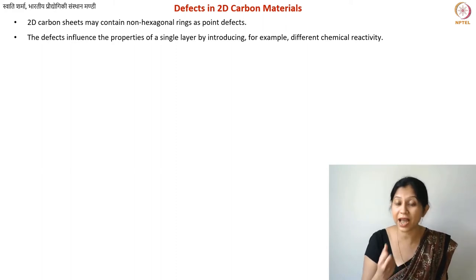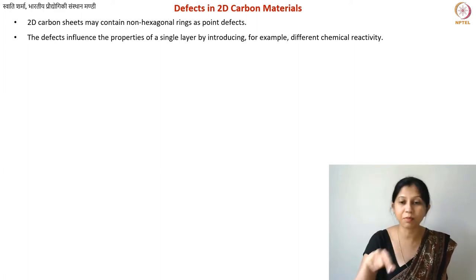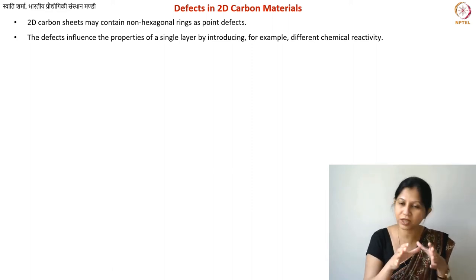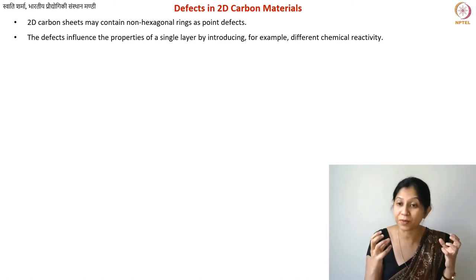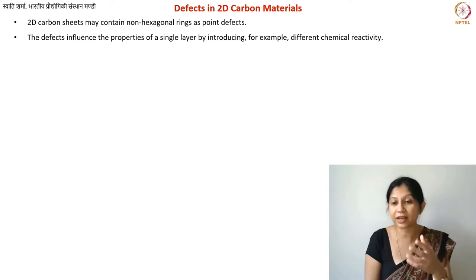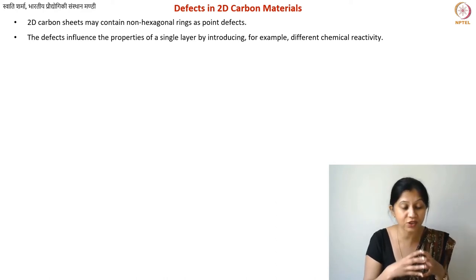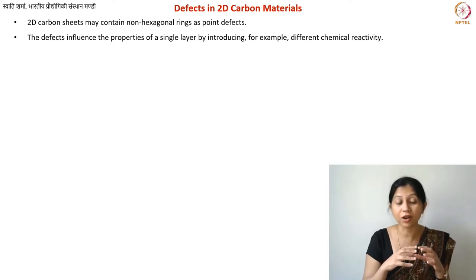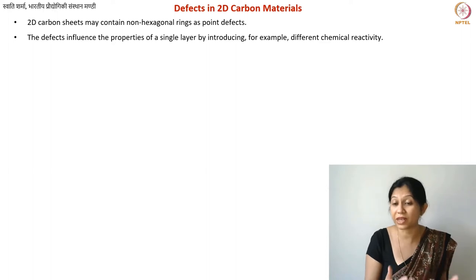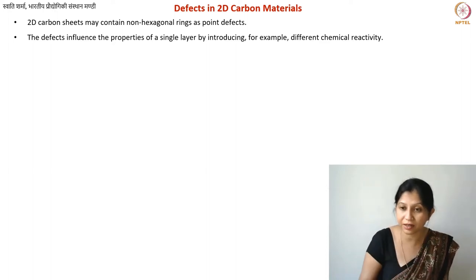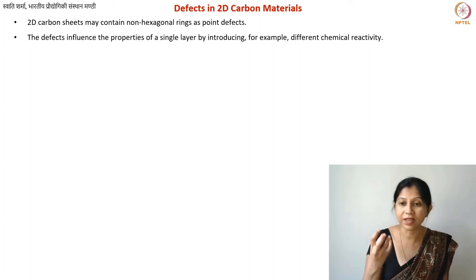Sometimes defects introduce new chemical reactivity. In principle, graphene should be relatively inert, but if you have an unpaired electron or a dangling bond somewhere, or a structure which has a lot of strain, your graphene may be more reactive compared to defect-free graphene. So people actually introduce defects in order to get certain special types of chemical reactivity. Also, grain boundaries in graphene lead to a different pattern of electrical conductivity along that boundary compared to the rest of the structure.